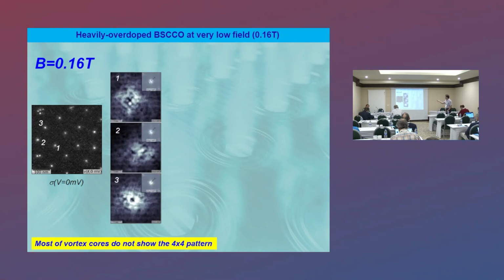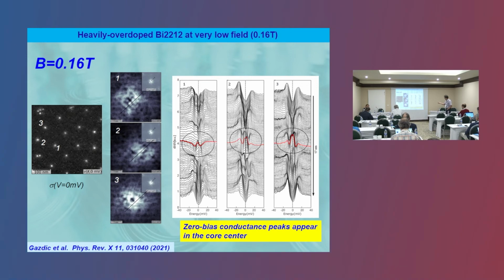So we decreased the field to 0.16 Tesla. And now this is the picture we get from 3 different vortices, where in some cases there is a remaining modulation of the conductance, but in most of the cases there is no more clear pattern of the conductance seen at high field. And now if you take the spectroscopy across these cores, so it's the same compound, same doping, just the field which is reduced, you get back the zero bias anomaly which is predicted by the BCS. So this is the first time where we observe what is predicted by the Wang and MacDonald calculation. But this is now done at very low field and on the heavily overdoped side of the phase diagram.